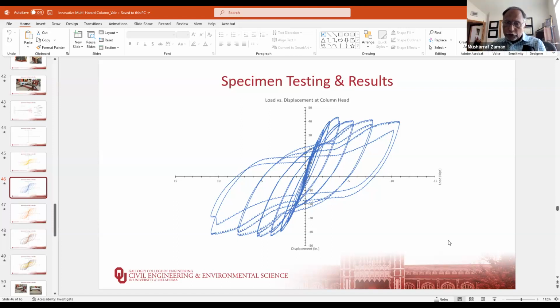Wonderful, very good explanation. So the next question is, will the contractors be able to attach or hang the cap forms to the columns as they normally do in case of reinforced concrete columns? Yes, absolutely. Once you place the concrete in the core between the steel and the FRP, it's got all of its capacity. It's designed essentially to be a cantilever, and as the concrete gains strength over time, it will get more and more. But once you place the concrete in the core and let it cure for a couple of days, you could put a significant amount of load on it. It's ready to go.